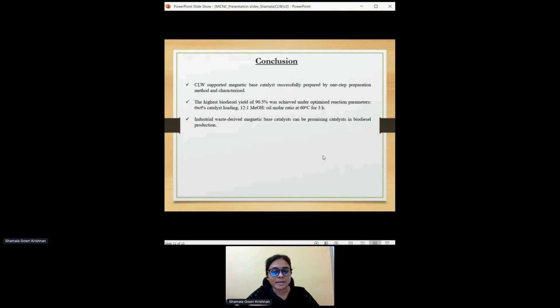In conclusion, carbide lime waste supported magnetic base catalyst was successfully prepared by one-step impregnation method, and we have characterized it by various analyses. And the highest biodiesel yield was achieved at 90.5% with optimized reaction conditions at 6 weight% catalyst loading, 12 to 1 methanol to oil molar ratio, at 60 degrees Celsius for 3 hours. And we can derive that industrial waste magnetic base catalyst can be a promising catalyst in biodiesel production.